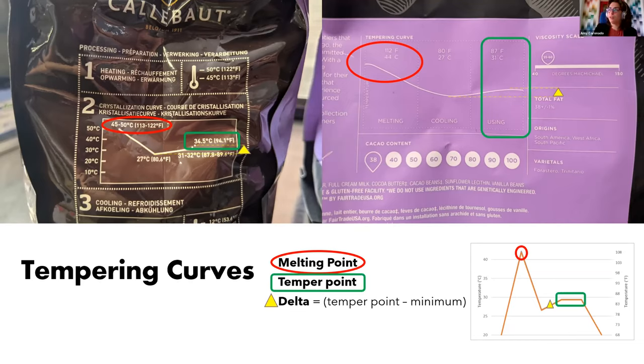You can put it in the fridge. I will get into the fridge stuff that I was talking about a little bit. You can put it in the fridge for a little while to jumpstart that cooling. I would not leave it in the fridge to cool for the entire process. So that might help bring the temperature down quickly. But in general, you want to work in a temperature controlled environment. So if you can get to a place that has air conditioning, great. In our office, we had to get a separate air conditioning unit that vents to the outside for the room where we temper chocolate, because it needs to be low humidity and stay generally pretty cool while we're working.